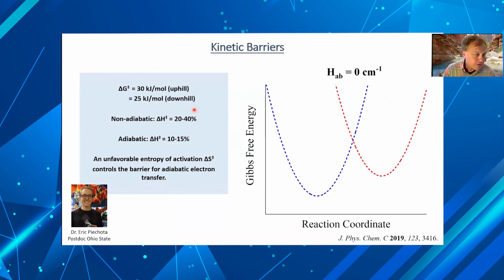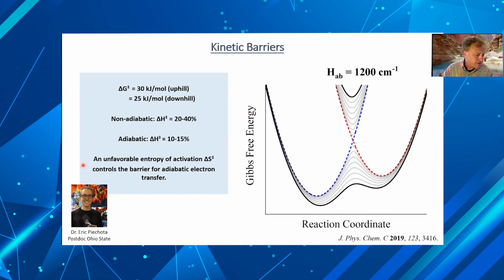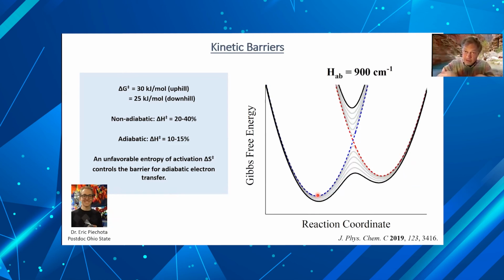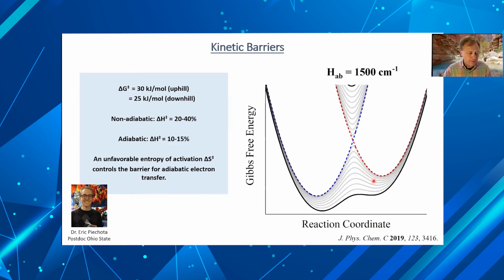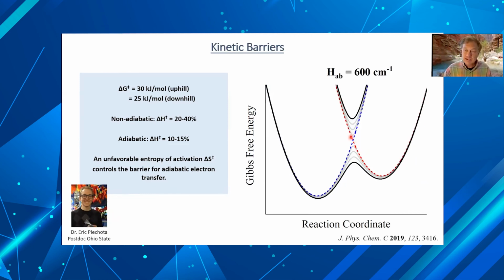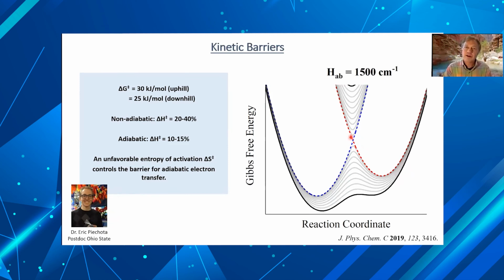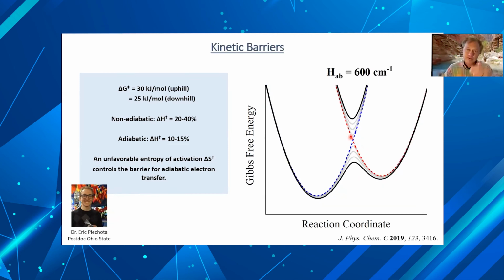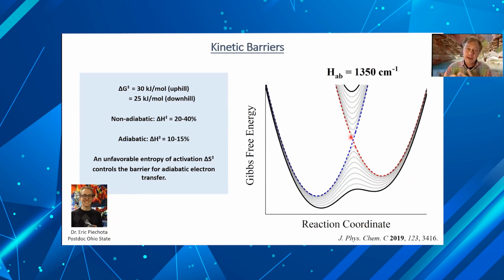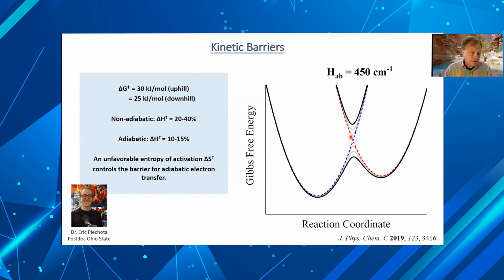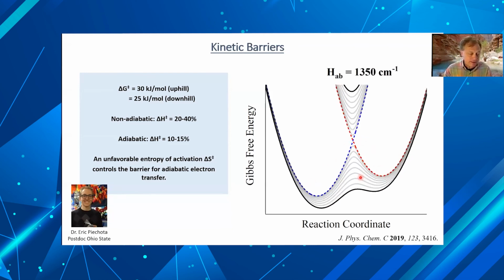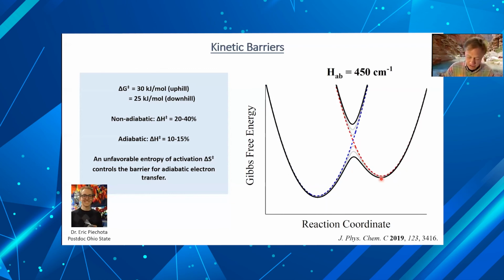Eric Piechota, who was a graduate student here, went and studied the reactions, and I have been a little long-winded, so I'm going to quit here, but what he found was that the Marcus-Gerischer theory, if you will, predicts that as you increase the coupling by having a more conjugated bridge as opposed to one that's orthogonal, you do change the Gibbs free energy. The minimum of these curves change. But the intersection point, the barrier, did not change very much. And using an Eyring analysis, he saw that there was this compensation between the entropy of activation and the enthalpies. So the barrier was pretty much the same, but the coupling was certainly changing the overall Gibbs free energy change.